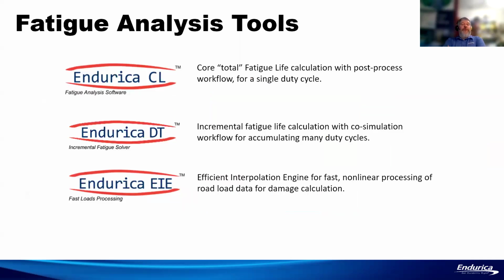Now, when you use Endurica, there are three tools that we talk about. One is the Endurica CL, and we have Endurica DT, and we have Endurica EIE. They're really divided by the kind of workflow that they support. Endurica CL is a post-process only workflow where you run your finite element model, then run Endurica CL as a post-process on the stress strain results from the finite element model, and it outputs either safety factor or fatigue life. The key thing there is it's a single duty cycle, and you're talking about repeats or safety factor.